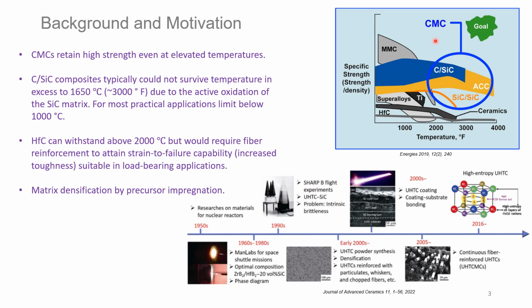On the other hand, ceramic matrix composites such as carbon-SiC, advanced carbon-carbon, or SiC materials, which are grouped together here, may retain high strength at elevated temperatures, which are key for air-breathing vehicles. However, long-term application temperature for carbon-SiC material could not exceed 1650 degrees centigrade due to the active oxidation of the SiC matrix. Also, carbon-carbon matrix starts oxidation above 500 degrees C without a protective layer.